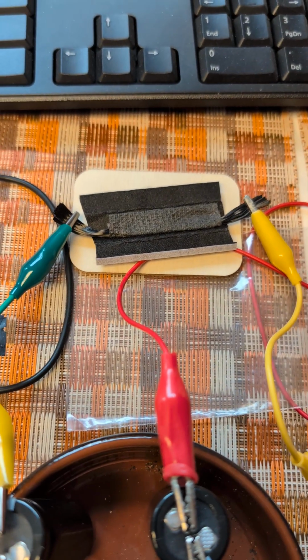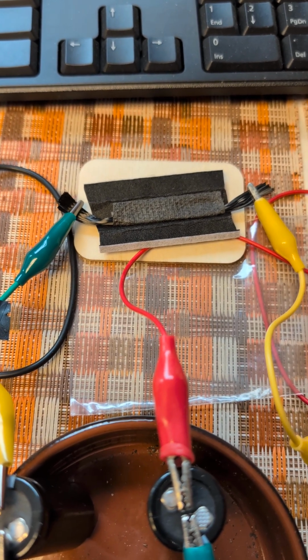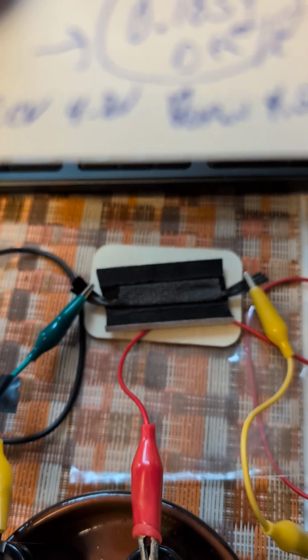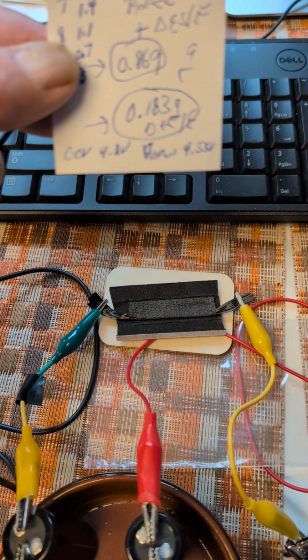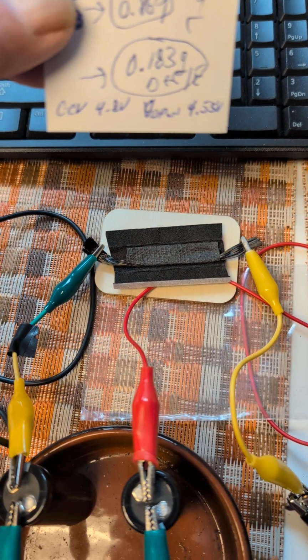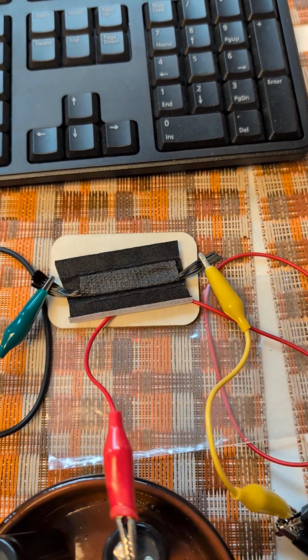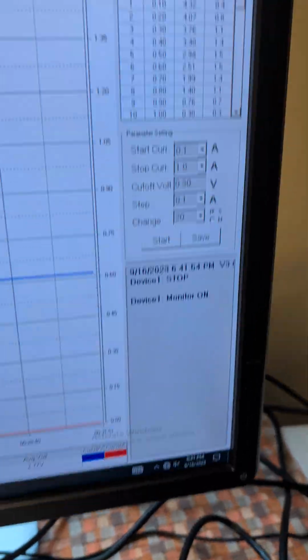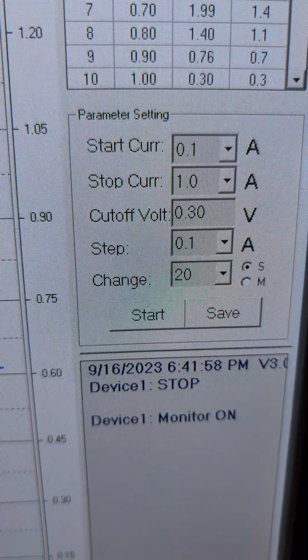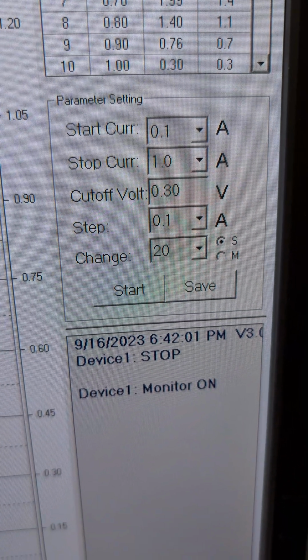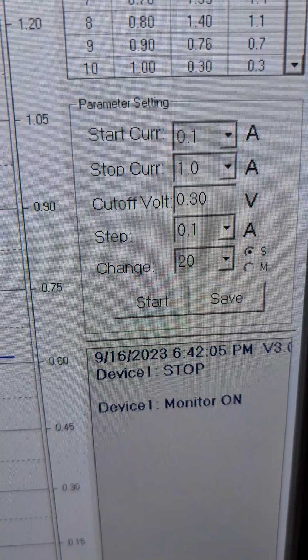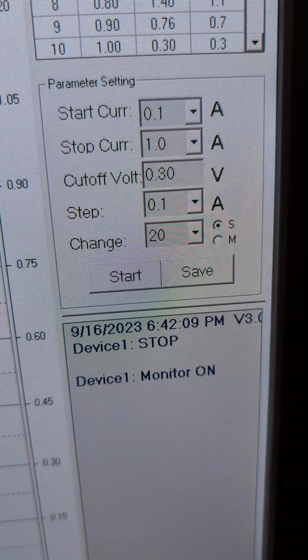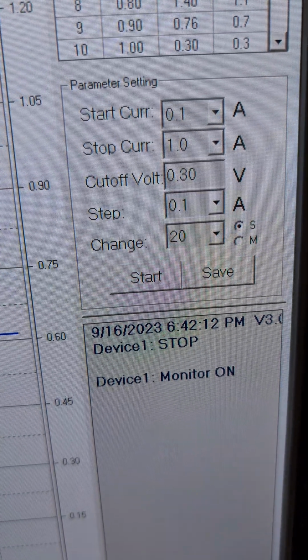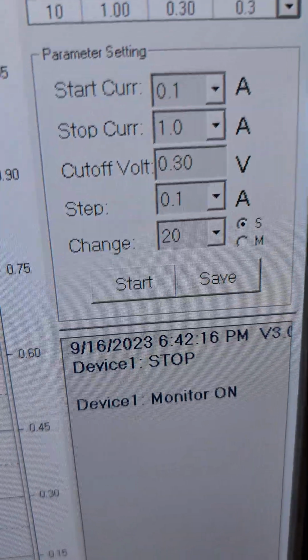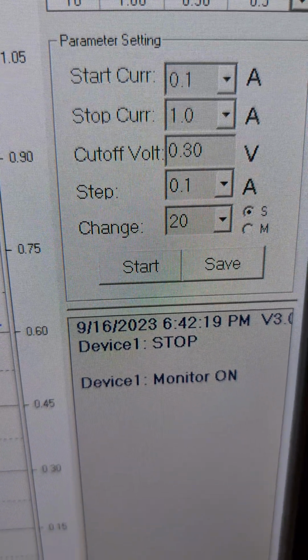And according to what we're seeing, I've got numbers all over the place here. Generally, bring it up to 4.8 volts. And then the open voltage, we sometimes get right around 4.55 volts, open voltage before we start the step level analysis. So we start at 0.1 amp. We go up to 1.0 amp current draw. The cutoff voltage is 0.30 volts. Never want to go down to zero with the supercaps. In steps of 1/10 of an amp. And we've gone now to 20-second changes.